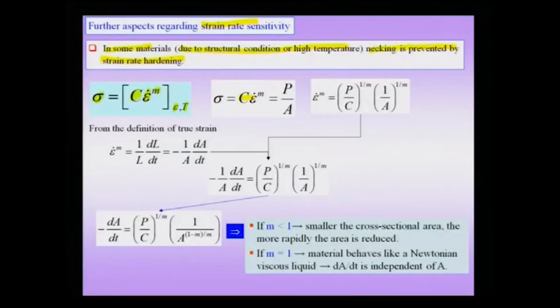So, we can of course write sigma as P by A, load per unit area, which is the definition of stress, and I can rewrite the same equation using this. I can put sigma equal to C epsilon dot power m, and therefore I can write epsilon dot power m as P by C into 1 by A, so epsilon dot is (P/C) to the power 1 by m into 1 by A to the power 1 by m. And from the definition of true strain rate, epsilon dot is 1 by L dL by dt.